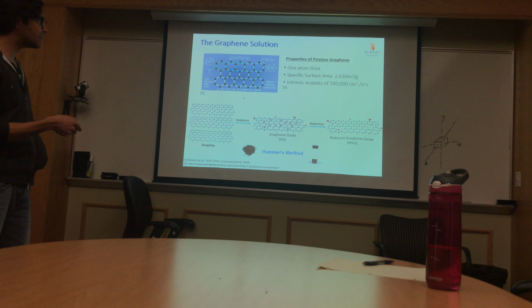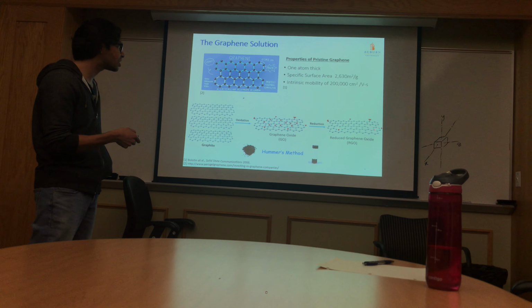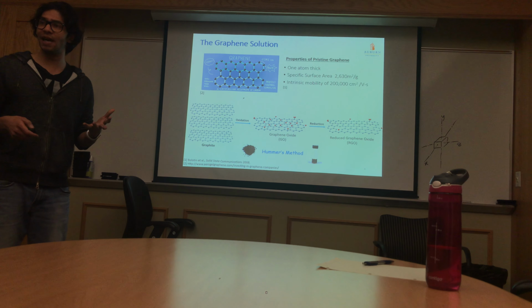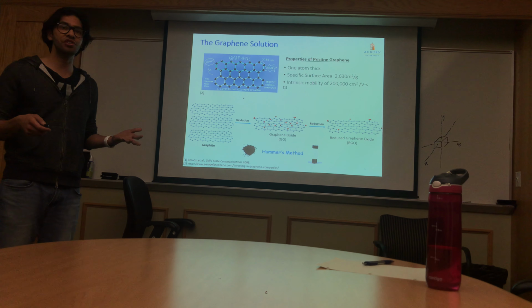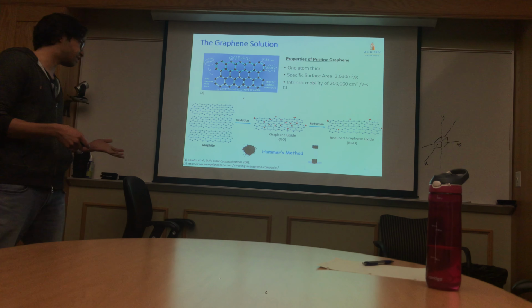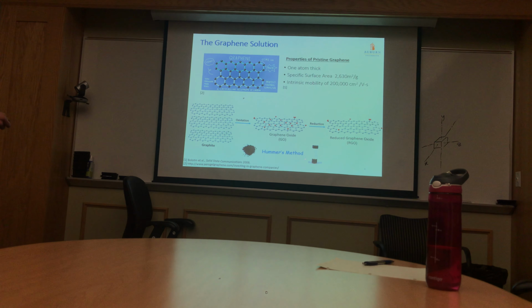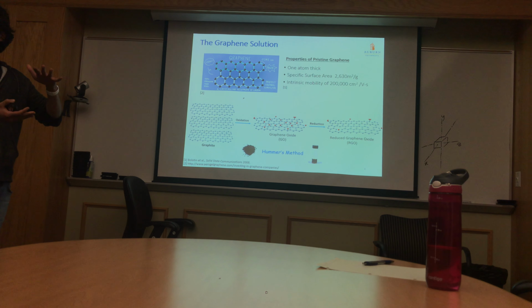However, there is a similar molecule called reduced graphene oxide, which is similar to graphene except that it has a few oxygen functional groups and defects on it. It can be utilized, and has been utilized by researchers, to develop applications of graphene. Now, reduced graphene oxide can be made from graphite. Graphite is nothing but stacks of graphene stacked together. To make reduced graphene oxide, we need to exfoliate these layers. We do that by oxidation.